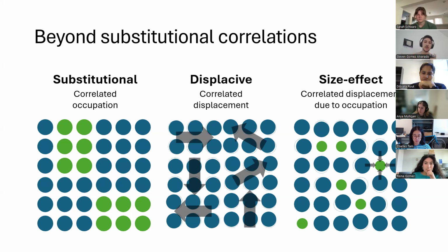And so you get a combination of substitution correlated with displacement. Okay. And for all three of these examples, we want to see what kind of features we might expect in the delta PDF. The reason is that usually when you grow a crystal, you don't really know what's happening with the atoms at the local scale. The first thing you do is take a diffraction pattern. So you don't always have a good understanding of what's going on atomistically, but you want to know how to interpret the delta PDF once you obtain it from your diffraction.